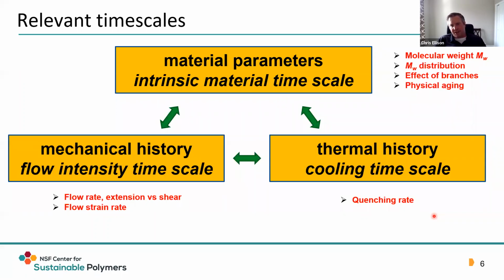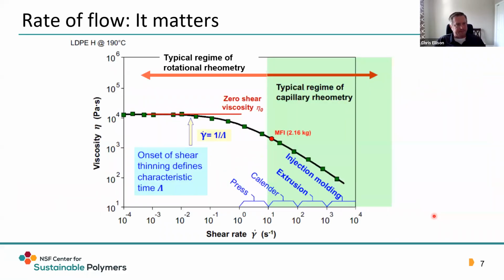But you have to think about those material timescales and how they work with the process, which come from the mechanical history, the flow intensity timescale, which can be different depending on the process you're using, and also the thermal history. Thermal history in particular is important by way of how quench rates may control internal stress in the system, or the crystallization kinetics, and ultimately the crystal content. So these 3 timescales are really important.